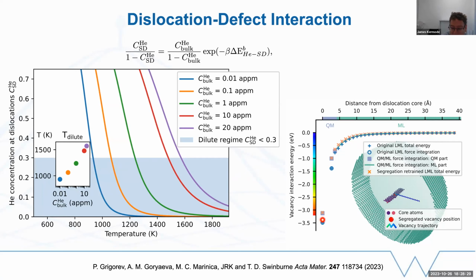But down here where the dislocation and the vacancy are very close together, there's a significant disagreement between the original machine learning potential and the reference results that we got when we used quantum mechanics. However, if we update the potential, we do this refitting of the potential, we get the orange points here, and you can see that that matches very well with the reference result. So if we wanted to study more different configurations, do more compositional or structural averaging, we'd be able to do that just with the potential, which would be very much faster.